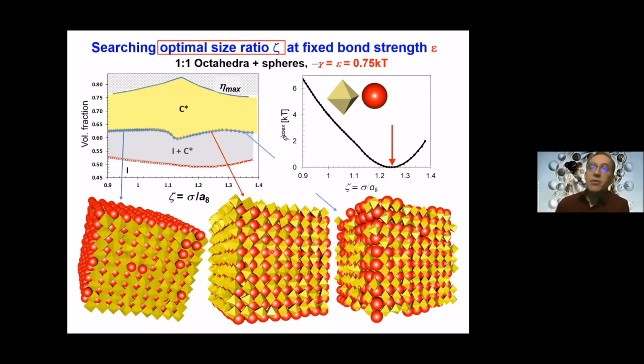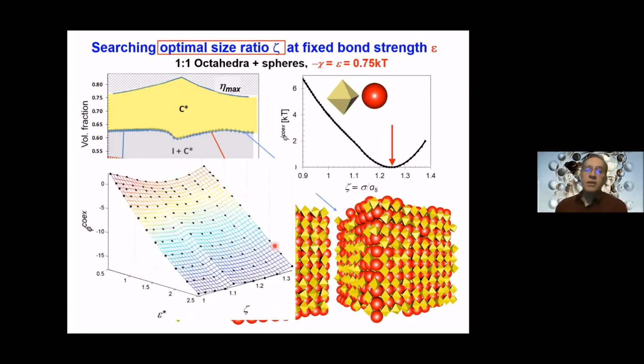In reality, what thermodynamics tells me is that it's really this free energy that determines what structure is more stable. So it's this. And it's a calculation you can also do in two dimensions, here shown as a function of not just zeta, but also epsilon. And expectedly, you can see that the free energy decreases as you increase epsilon. That makes this contact energy more favorable to the compound.